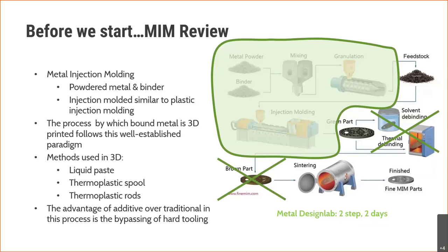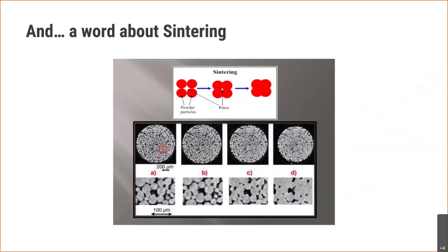which is a liquefied material. If you think of toothpaste, that's the consistency the actual feedstock is like. It's basically a toothpaste-like material that consists mostly of metal powder that's in a suspension. We take that metal powder and then we 3D print your part, and then we just send it to the sintering furnace. It's a two-step process, and you can have parts in as little as 2 days or less.